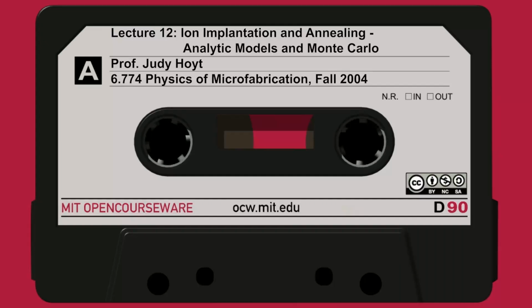So this has tremendous control, very good accuracy, and it's very reproducible. It has good dynamic range because you can adjust your beam current down from something like 0.01 microamps. If you want to do a very, very low dose, you're putting in at a very slow rate. You put the ions in and you integrate them up. Or you can do it if you have a very high dose. You might have to have a milliamp of beam current going into the wafer. Either way, you get very, very good control.